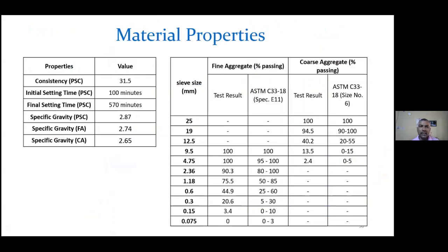Now for this whole thing, we have used certain materials. It shows the material properties of the cement and the aggregates that we have used. You can see they're all standard tests like setting time, specific gravity of cement, and Portland slag cement we have used, fine aggregate specific gravity, and specific gravity of coarse aggregate. And this is the gradation of the coarse aggregate and fine aggregate, and they are all within the limit of the code.